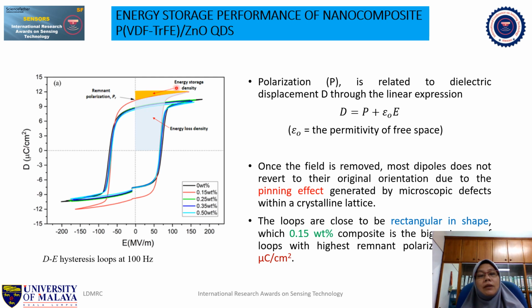density, which is shown by the orange color here, which can be obtained from the area of this part of the hysteresis loop, and energy loss density, which is indicated by the blue color of this hysteresis loop. So from this figure, we identify that the loop produced by hysteresis measurement is rectangular in shape, and 0.15 weight% of zinc oxide in the polymer host gives the highest remnant polarization, as indicated in this figure here.